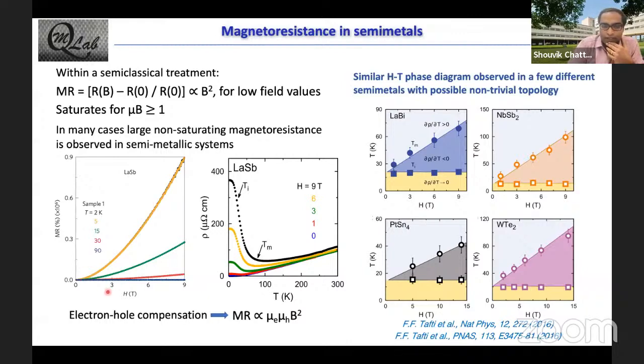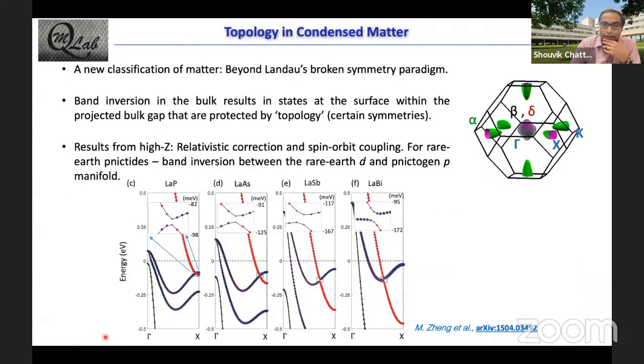And one does expect to have this sort of band inversion in this class of materials, the rare earth monopnictides, where basically you expect a band inversion between the rare earth d and pnictogen p states, as is shown here, and you would expect that you will have non-trivial surface states residing in this projected gap.